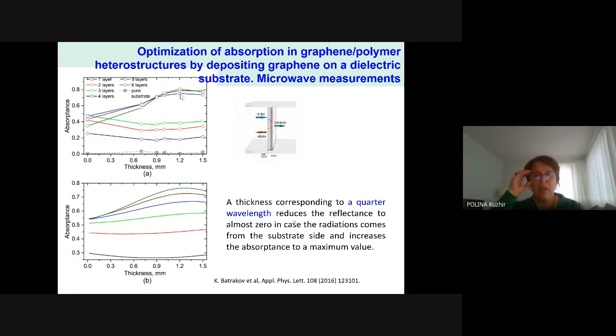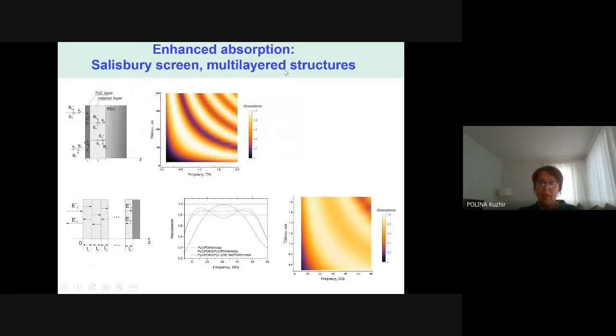We experimentally observed more than 80% absorption for the sandwich composed of 4, 5, and 6 layers.